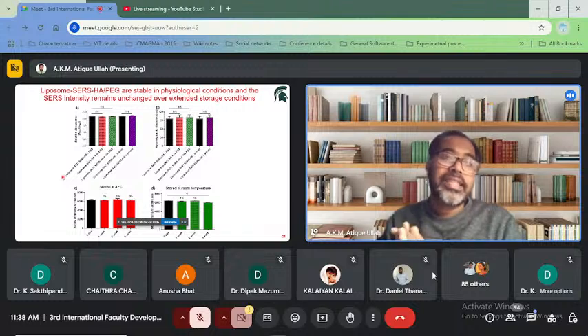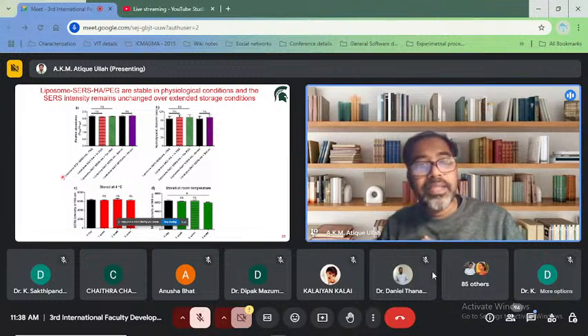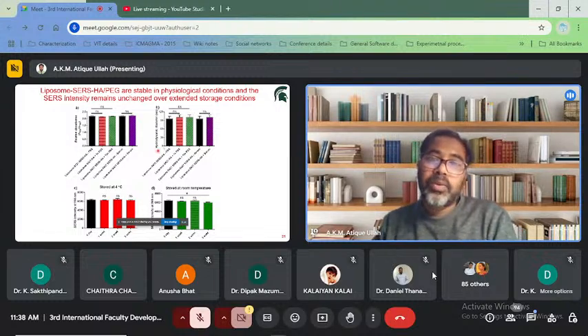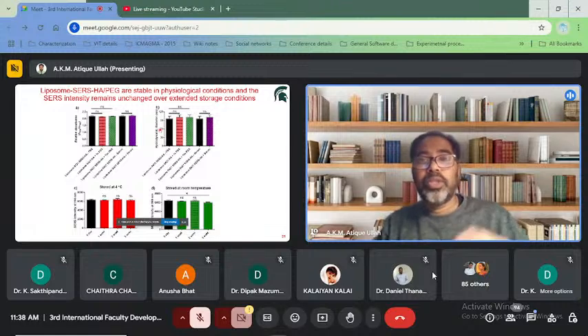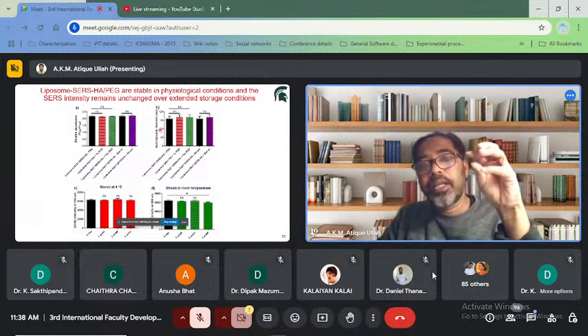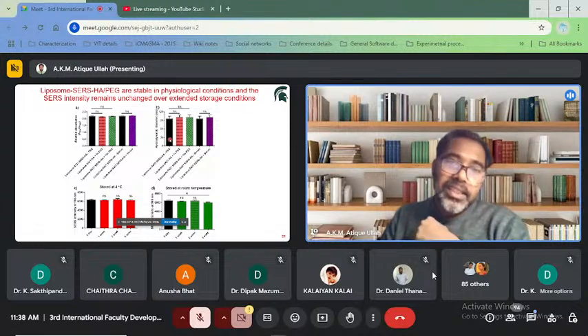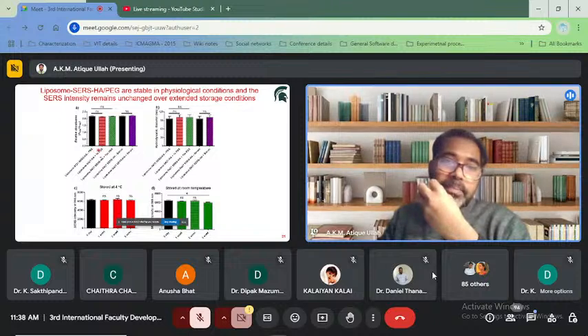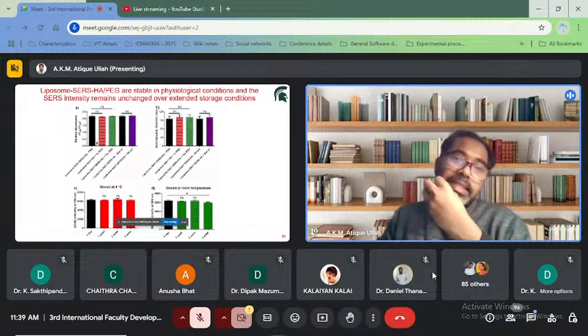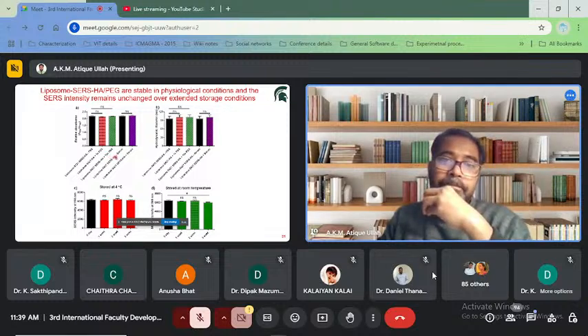Then we also checked the stability. The stability assessment was done through two different experiments. One is UV-Vis, another one is hydrodynamic diameter. And we considered the nanoparticles' stability in physiological conditions, that is in PBS and serum. You can see minus PBS and plus PBS, that is without PBS and in PBS. You can see there is no change in absorbance. And also it is in 1x PBS and 10x PBS. And also you can see our nanoparticles are not affected by the serum. So this is the UV-Vis.